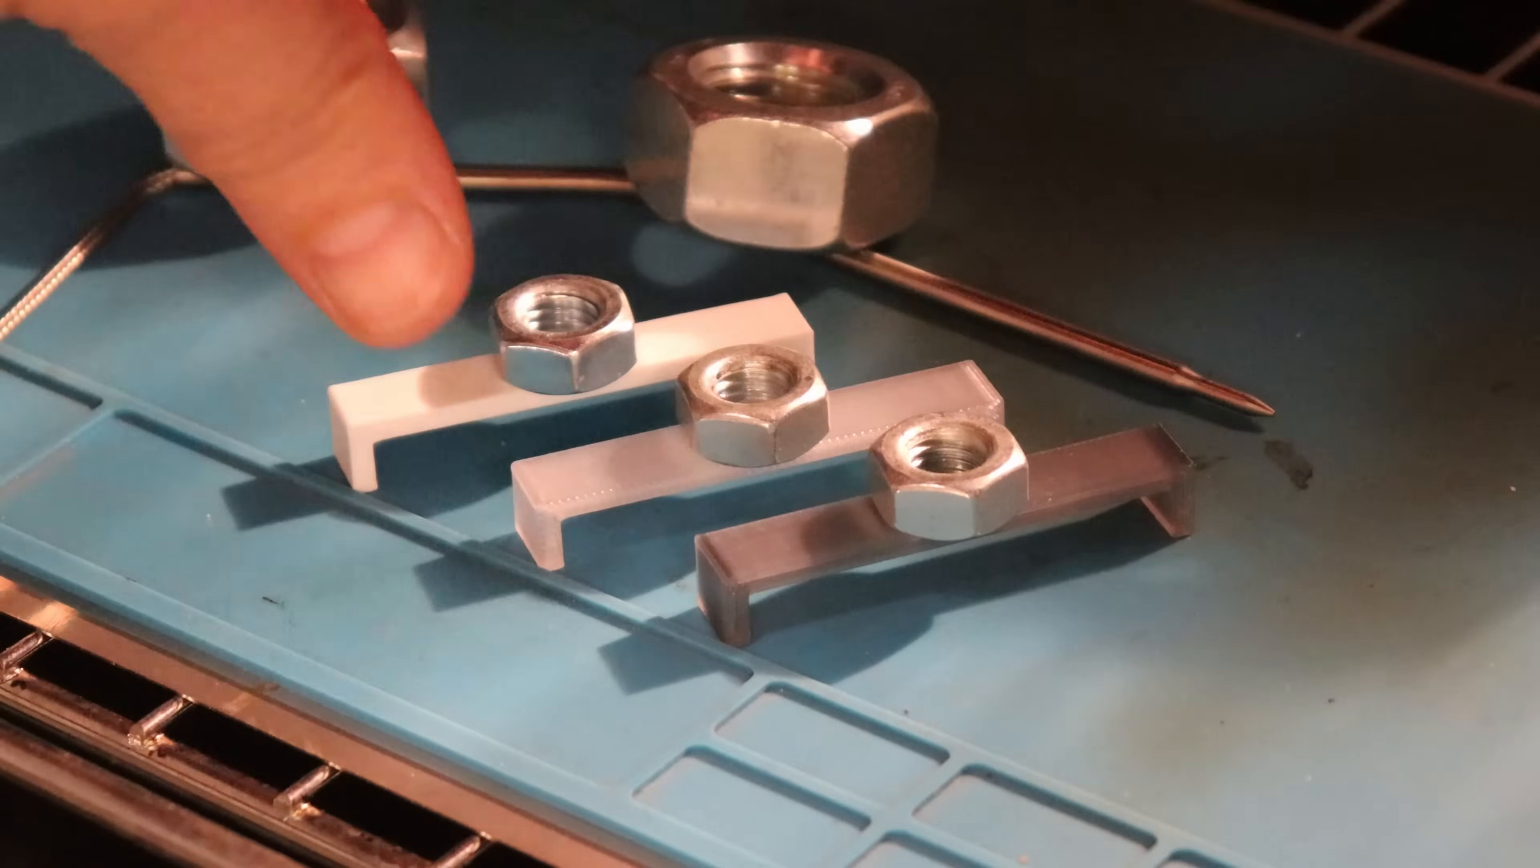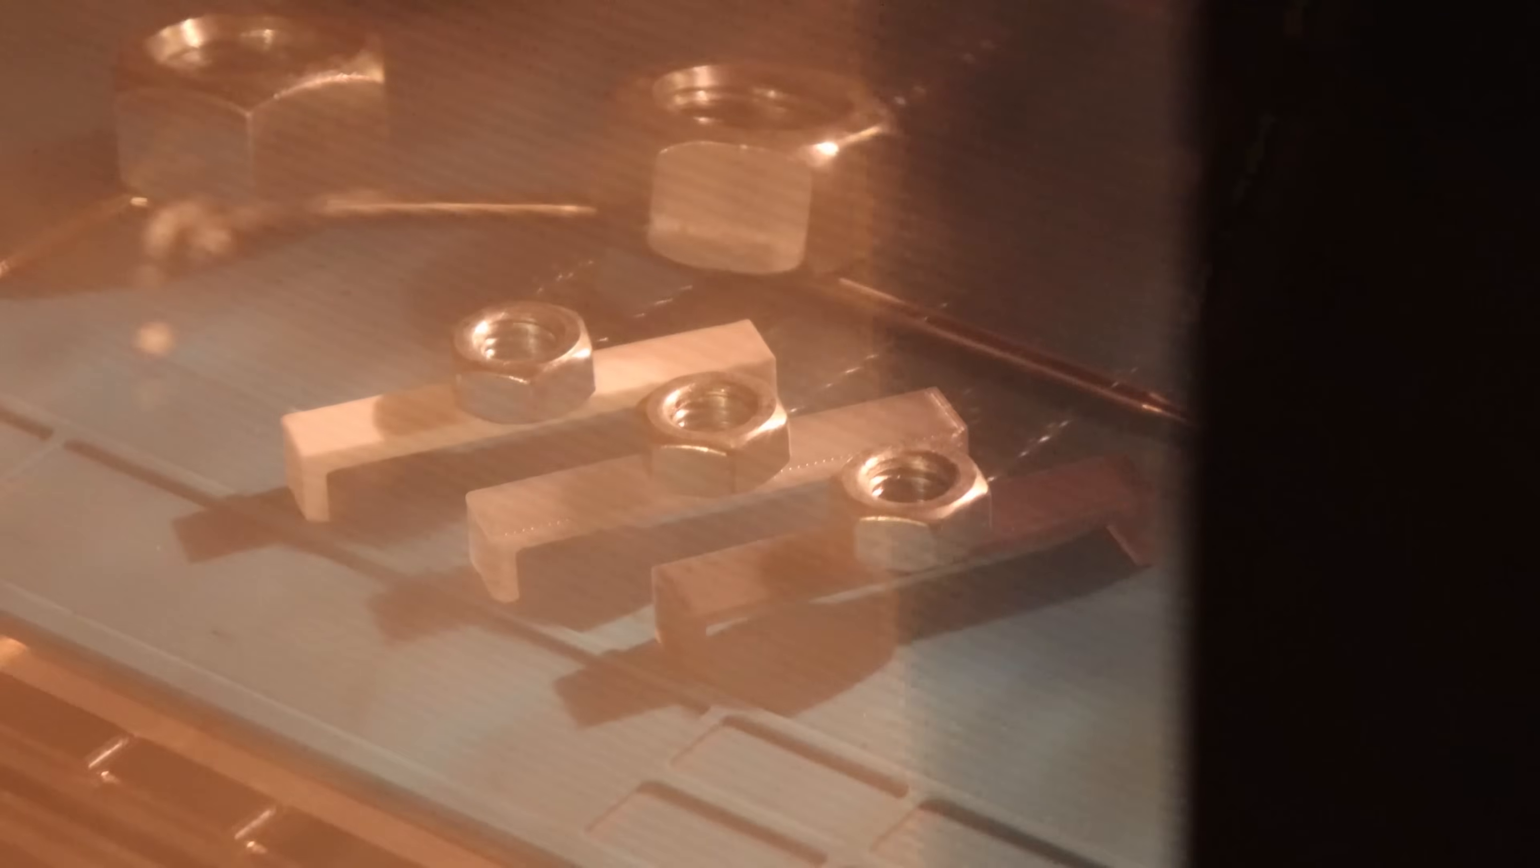The temperature test in the oven where I want to record the temperature of the first deformation. And this is sped up timelapse video. And they all started to deform above 100 degrees Celsius, but again I could see some differences between the colors. The black was the best in this case. I stopped the experiment at 160 degrees Celsius.